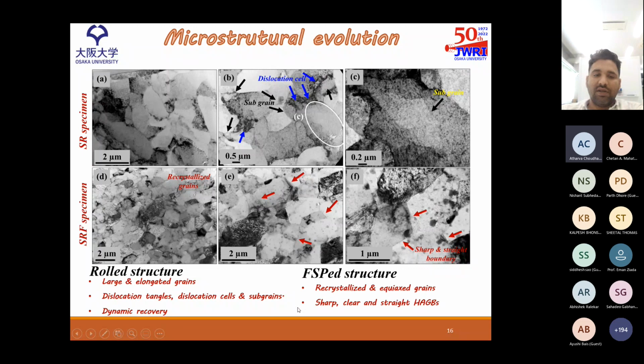And in the FSP structure, a recrystallized microstructure with equiaxed grains can be visualized here. Most of the boundaries, we can see, are high angle grain boundaries with sharp and clear features.